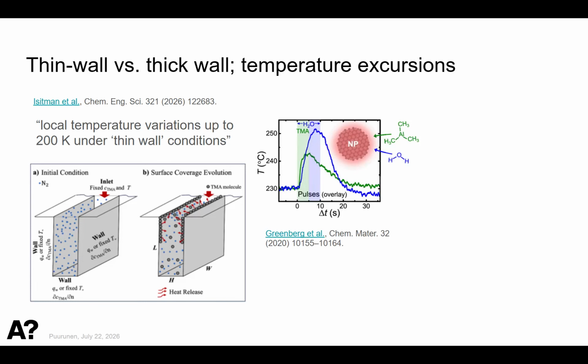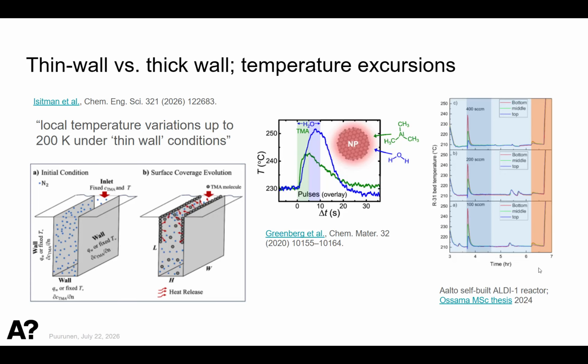And is that realistic? Well, this has not been paid attention to very much in the literature, but a few years ago we started thinking of this, and some others as well. Here is a paper from Greenberg et al., where they have measured a 20-degree increase for particle coating. And at Aalto we have built our ALD reactor, and this is from a master's thesis 2 years ago, where we observed that once we start delivering our reactant, zinc acetylacetonate in that case, we do get a temperature increase, and in the highest case it was a 40-degree increase. So this is clearly something that should be paid attention to, especially when scaling up ALD processes for powders.